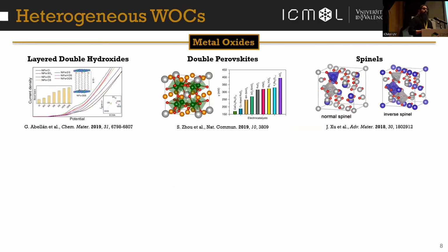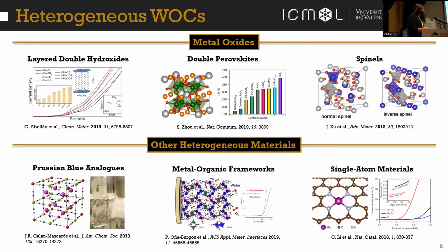So regarding heterogeneous conditions, the most interesting are metal oxides, like layered double hydroxides, double perovskites, spinels. And we also have other types of heterogeneous catalysts that are not oxides, such as Prussian blue analogs, metal organic frameworks, or single atom materials. The problem with these materials is that as they are heterogeneous materials, they are more difficult to characterize and to process, but they have a very good stability under most of the conditions we use.